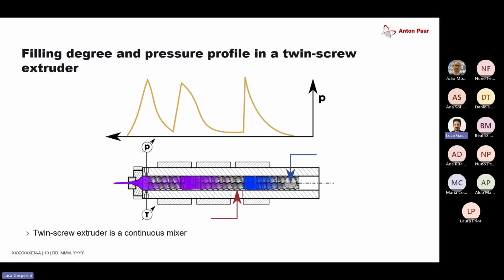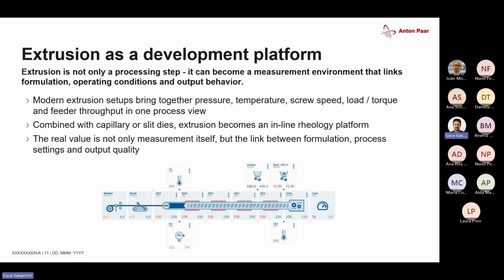And we had this issue: the process worked fine, we started at some point, but what we got out, we couldn't create a film from. So we checked, we could just open the liner and check. We had a very large mixing block right here with 4 or 5 kneading blocks chained together, and saw, hey, halfway through the kneading blocks, our material had already broken. So it wasn't really a film anymore. We tried extracting some material from the end of the kneading blocks and from the middle, and we saw that in the middle the material was the way we wanted it to be. This way we could greatly shorten the screw configuration process by opening the liner, looking at the material, and then just reducing the number of kneading blocks to get the result we want. So the whole extrusion is not just a production process, but also a development platform.